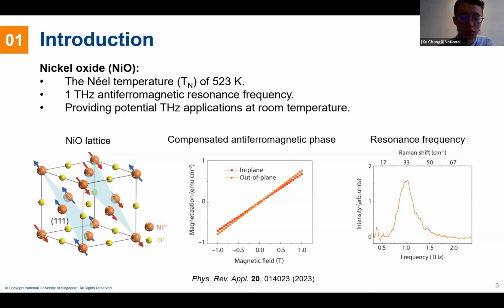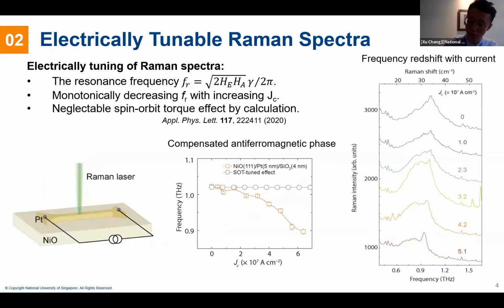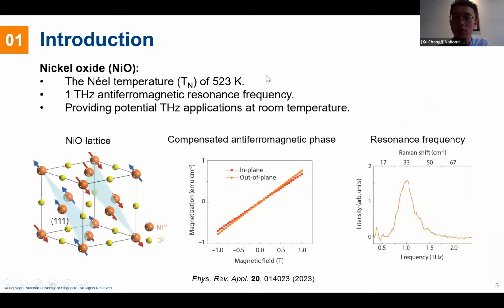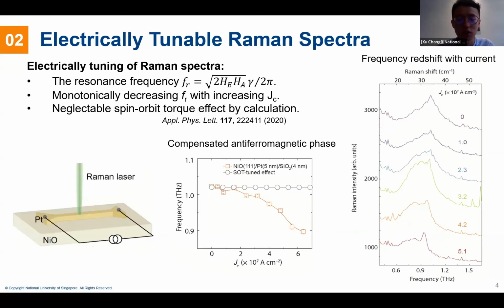Oh, I see. We haven't gotten the origin of the redshift at this point, but I have some intuitive explanation for this. The temperature can affect the exchange field as well as the anisotropy field. Because this material has a Néel temperature, above a certain temperature the exchange coupling will be smaller or stronger. So the temperature can actually affect the effective field. That's why I think the resonance frequency can be tuned with the temperature, because the coupling can be affected.